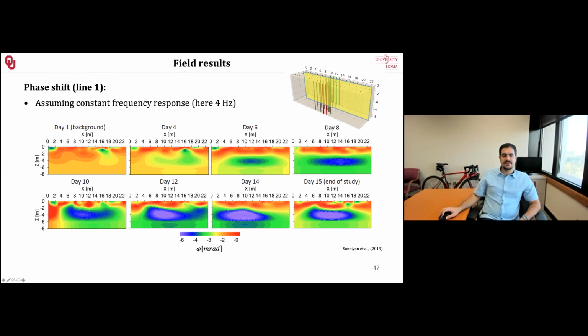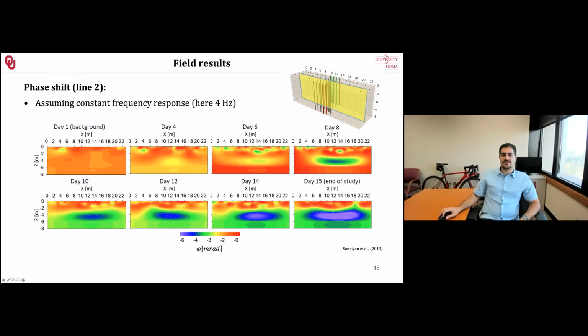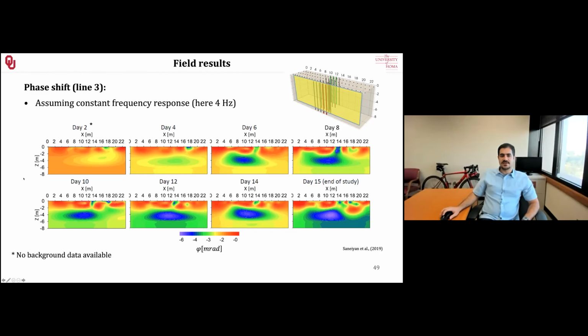For the second line, the same thing happens. The start was a bit delayed, I would say. And then, as you can see again, by the end of the experiment, we are clearly seeing the changes in the treatment area. And for the third line, we didn't have a background measurement because we didn't have a third line initially. Again, time consuming, right? But then we decided to add it. So we are seeing the same kind of effect, but maybe smaller compared to the other two, at least in the area. So I would say all of the precipitation sort of occurred closer to injection in the middle, and then there was nothing left for the last part.